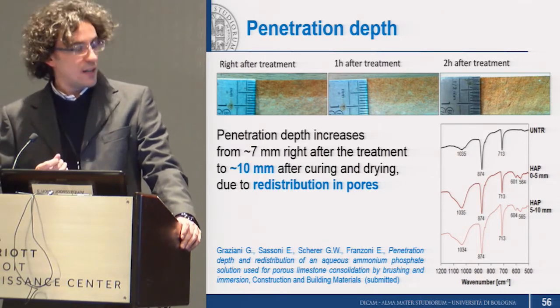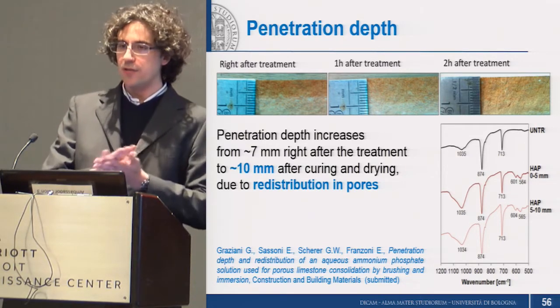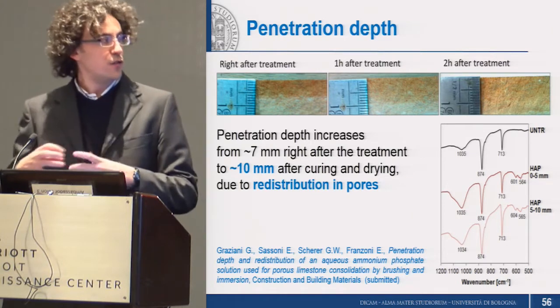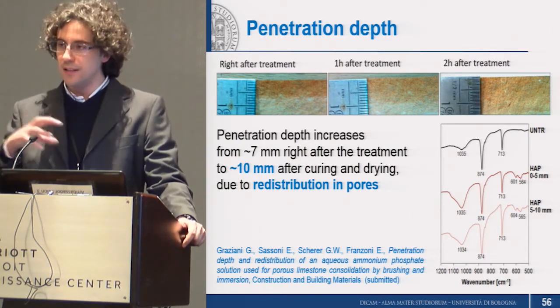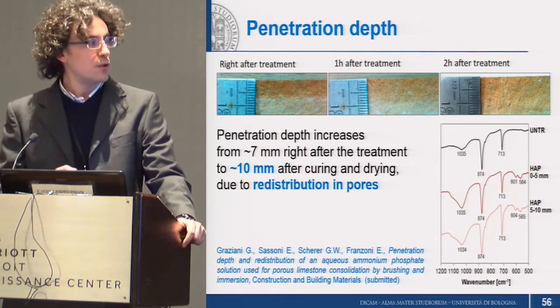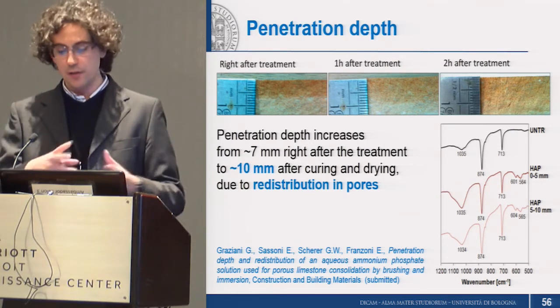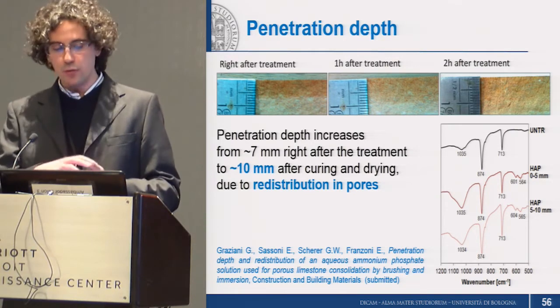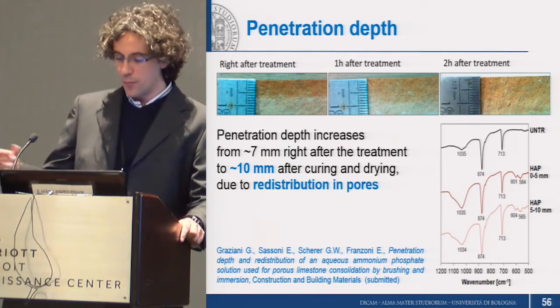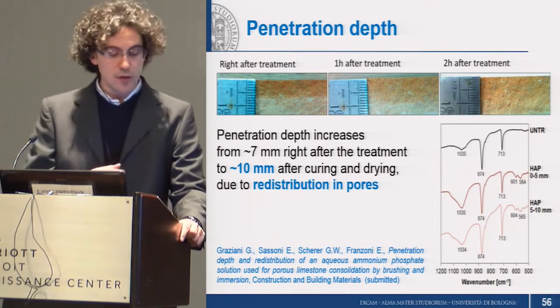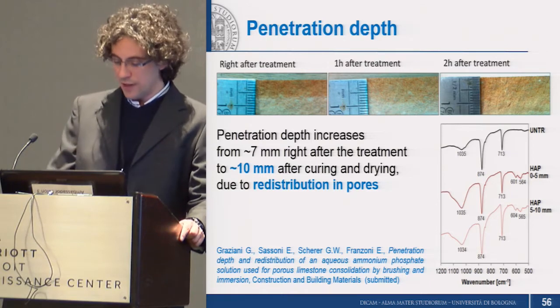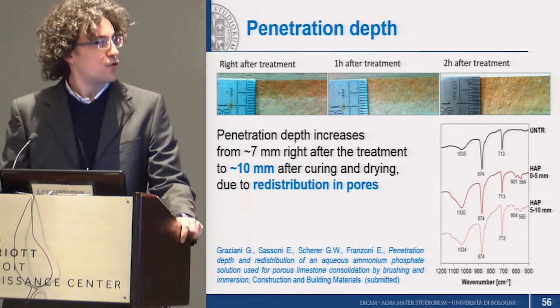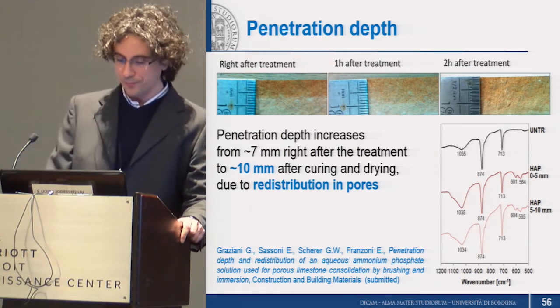And we also observed that after the initial application, over time, a redistribution of the consolidant in the pores takes place while it is still liquid. This is because the solution migrates towards smaller pores over time. And this is important because it allows an increase in the penetration depth over time.